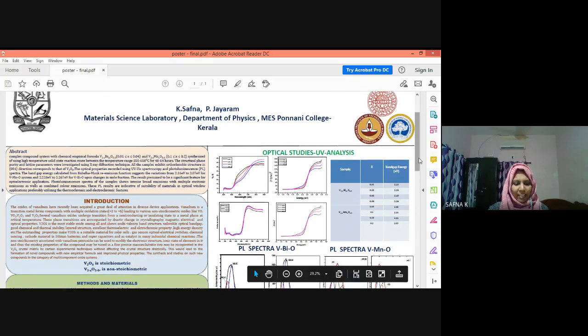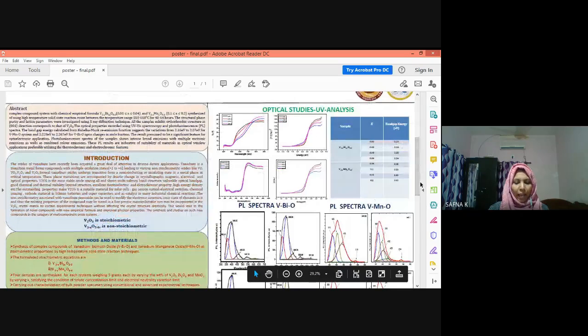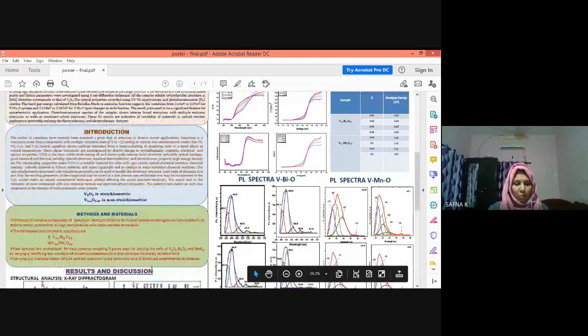Here we synthesized VBIO and VMNO complex compounds by solid-state reaction technique in the temperature range 540 degrees Celsius to 640 degrees Celsius and carried out different characterizations such as XRD, UV-visible, and photoluminescence spectra.